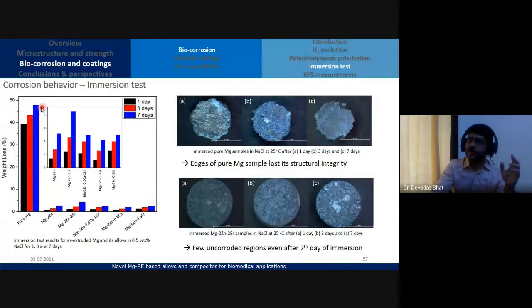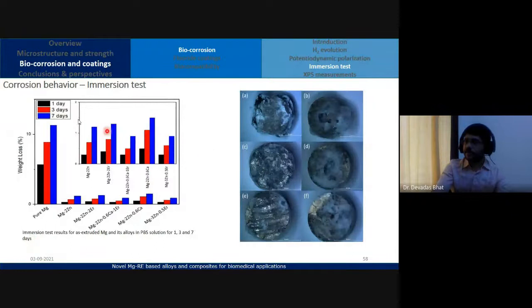As you can see here with the weight loss, within 1 day in the sodium chloride solution, we had about 38% weight loss for pure magnesium. Similarly for PBS, slightly reduced, but you can see here the formation of oxide, right?